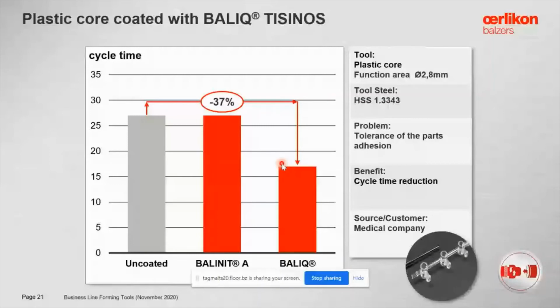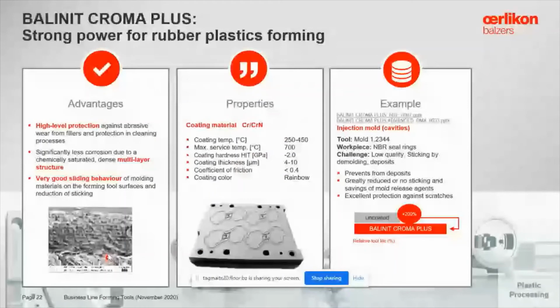We have special coatings like BALINIT Chroma Plus, which is strong for rubber and plastic forming. This is a high level of protection against abrasive or corrosive wear. It's a multi-layer structure. You can see here we have more than 28 to 32 layers with very good sliding behavior. This coating is chromium and chromium nitride based for better corrosion resistance. The coating has a max service temperature of 700 degrees centigrade, and this coating has a rainbow color. We recommend this coating especially for PVC molds or rubber molds.